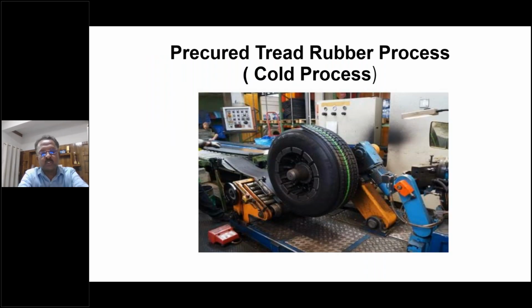In the pre-cure process, the worn-out tire is first inspected for defects, and it is buffed to remove the old tread pieces. After buffing, we apply a cement solution to the surface. Then after drying the cement, we place the pre-cure tread, a long piece of tread, and it is cured in an electric chamber or steam bonder.